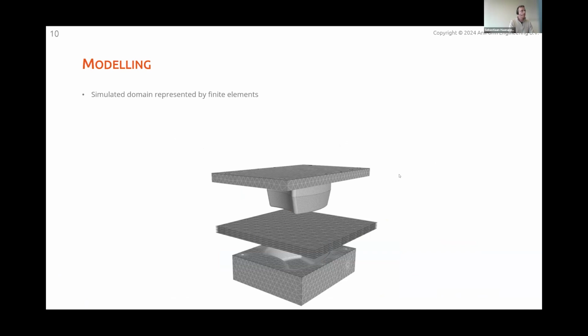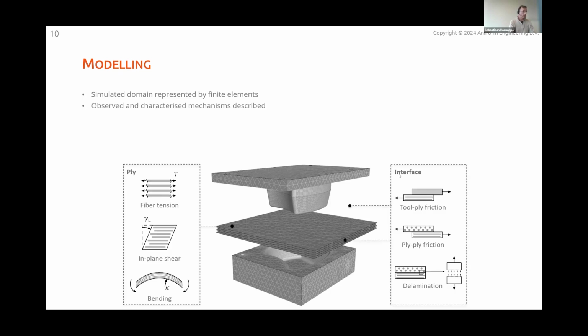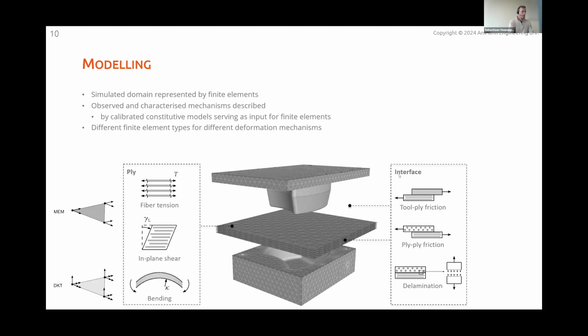Let's go back to the simulation. We want to create a model, and the domain we simulate is represented by finite elements like displayed here, all these triangles. Then in this model we describe the observed and characterized mechanisms. And these are described by calibrated constitutive models serving as an input for these finite elements. And we use different finite element types for the different deformation mechanisms. So we use membrane elements to describe fiber tension and in-plane shear. We use discrete Kirchhoff triangles to describe the out-of-plane bending of plies, and we use contact elements to describe ply-ply friction, but also tool-ply friction naturally.